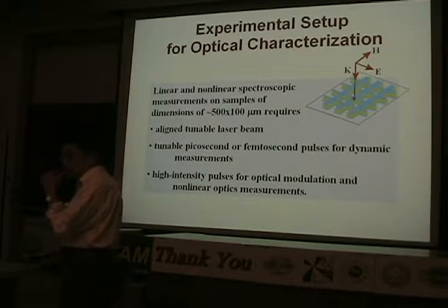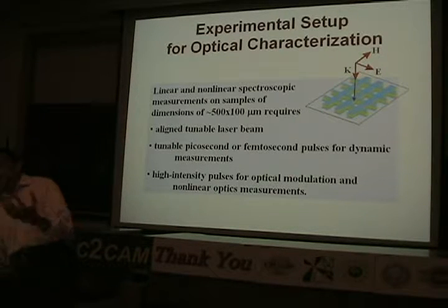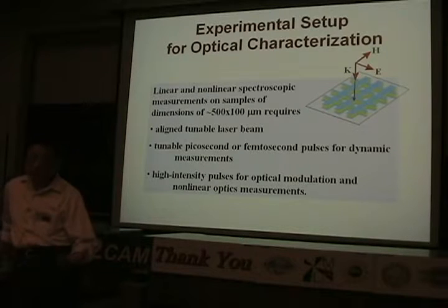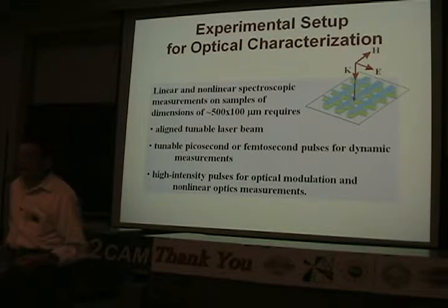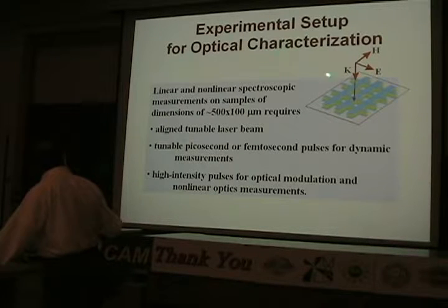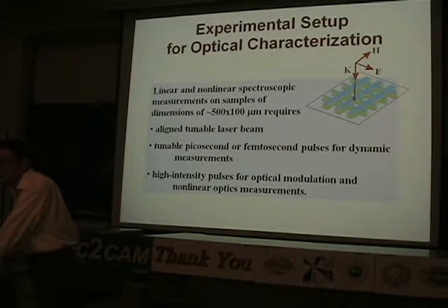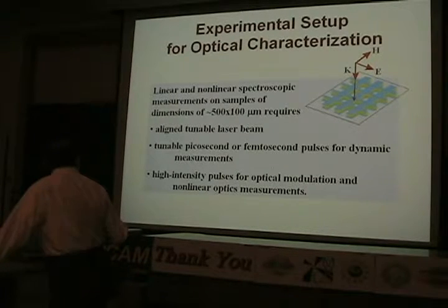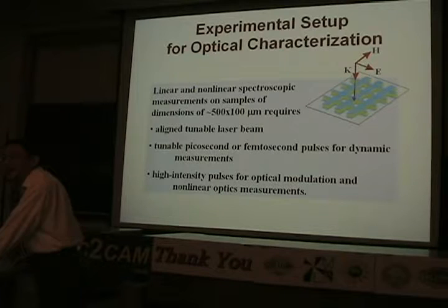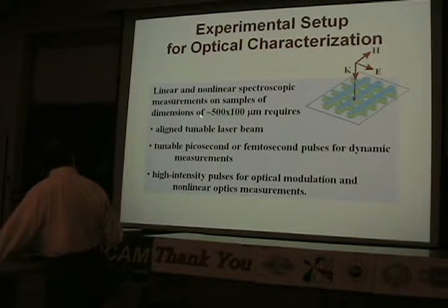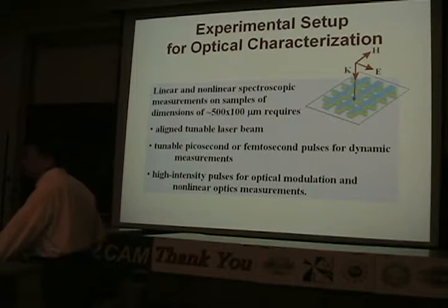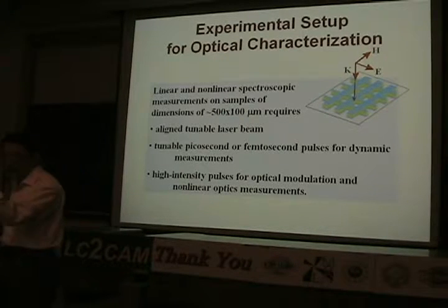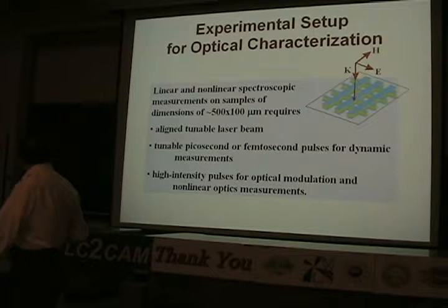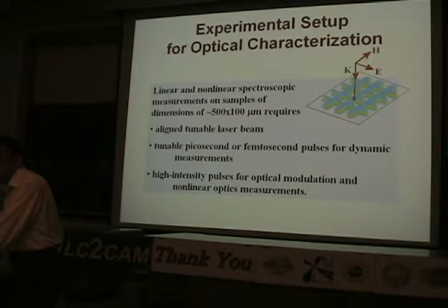So then we need to do experiment to show whether we indeed can get negative refractive index. And for the measurement, of course it's straightforward because it's a linear optical measurement. The only thing to worry about is the sample is extremely small. It takes some effort to have a sample that's 500 times 100 micron, so it's still tiny. Therefore we need to use laser to do this kind of measurements.